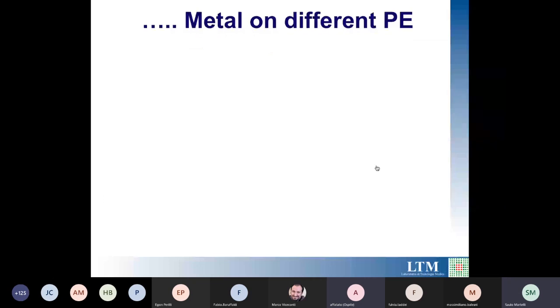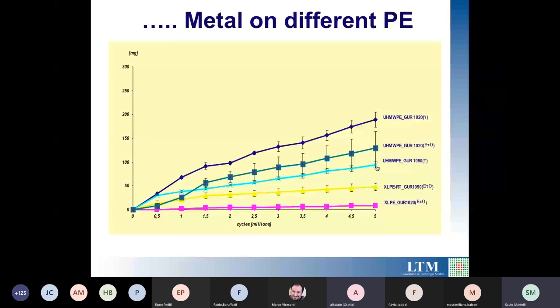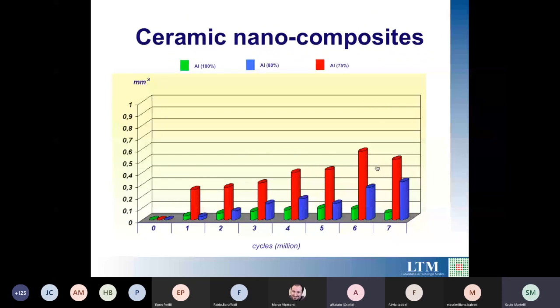In this result, we can observe some results of different polyethylene, ultra-high molecular weight polyethylene tested against metal alloy, with a good result obtained in comparison with the worldwide results about this composition. Other tests performed with our simulator were on ceramic nanocomposite with different percentages of alumina at 100%, 80% and 75%, with a good wear behavior with regard to the pure alumina.